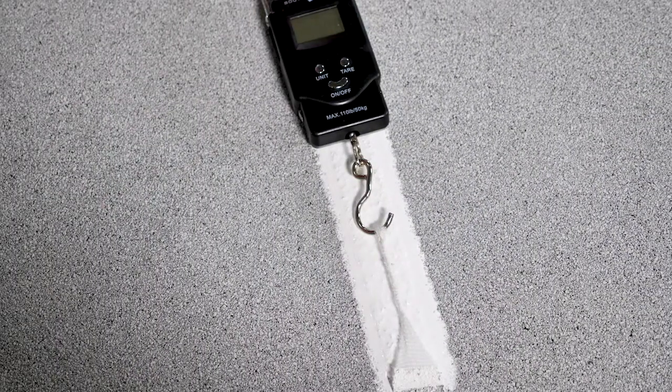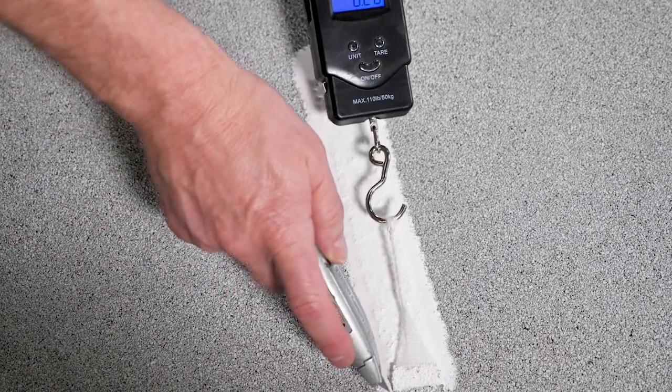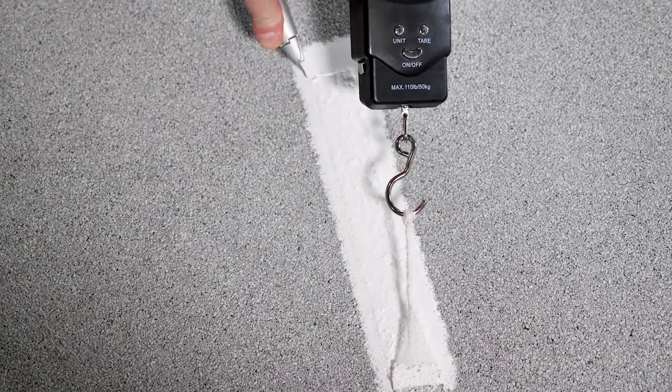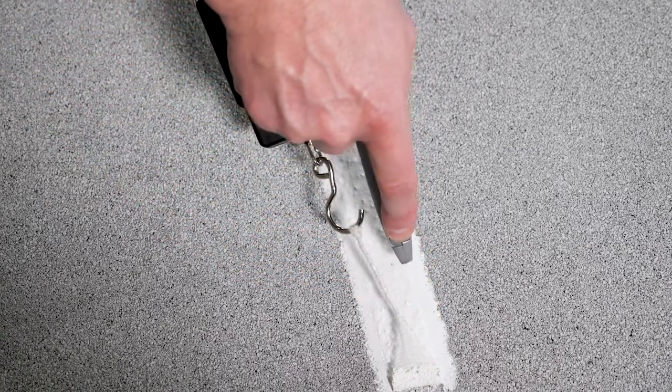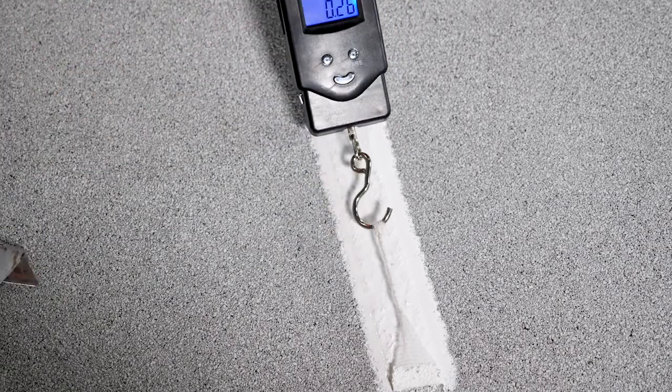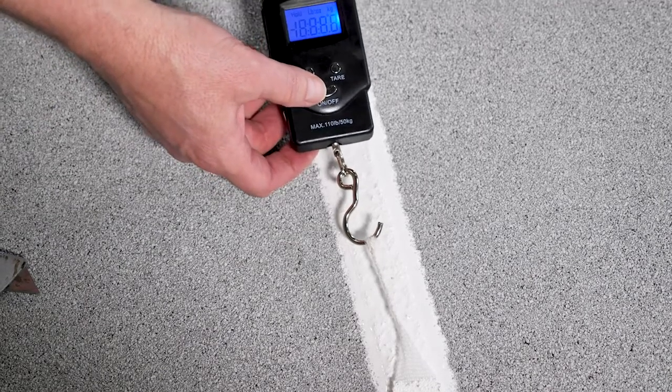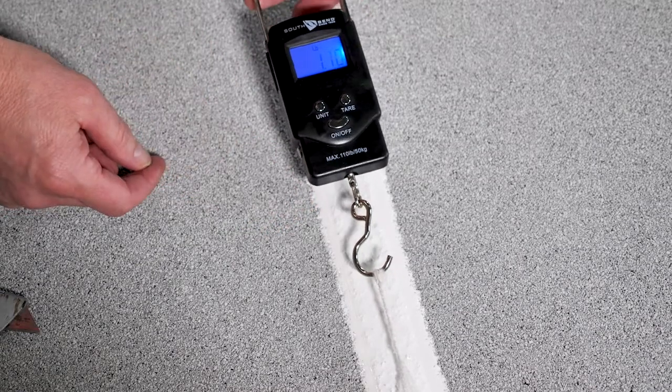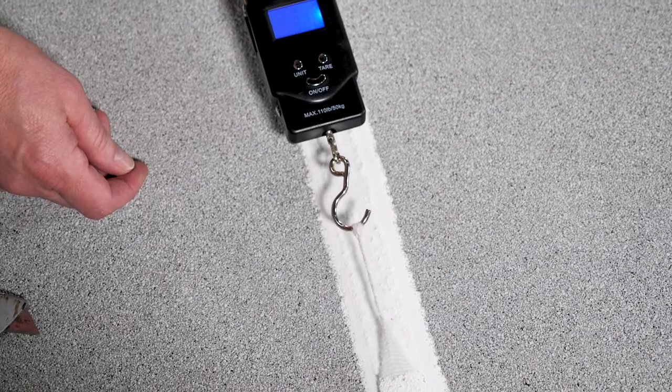We've tied the knot nicely and tightly into the hook. Before we do the test, always make sure to very lightly score with a sharp razor knife around the fabric, just to make sure when we do our pull test that we're getting the inch-wide value. You want to pull straight back as we go, and you can see values looking pretty good—10, 9...